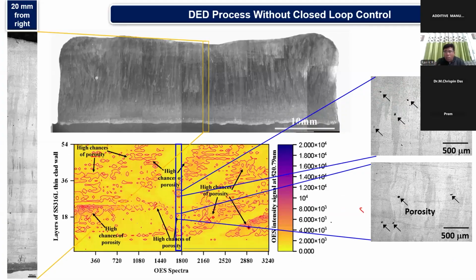Then with all this intensity map, we translated it in the form of the XYZ axis. Then we were able to identify these are the locations where I'm supposed to get porosities. You can see here we are getting porosity. This is what our system is actually detecting. This region I'm supposed to get porosity, and I'm getting the porosity.